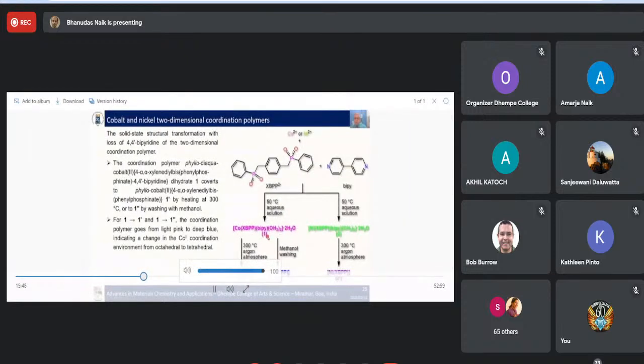With this, we have two compounds, 1 and 2 in this one here. These compounds are isostructural, they're exactly the same. They incorporate the one ligand and also a BP ligand here. And each metal center has 2 water molecules bound to them and 2 solvated water molecules, so dihydrates. And we found that if you heat these up at 200 degrees, and I'll show the TGA, which we used to discover this, we find that all the water molecules and the BP leave, and we're left with just the phosphonate cobalt structure here.